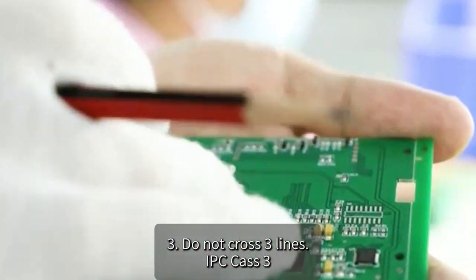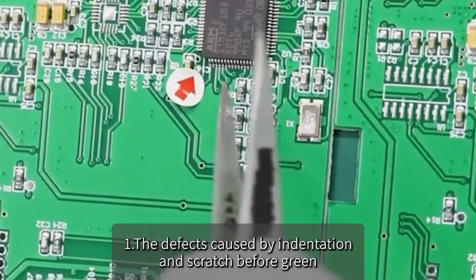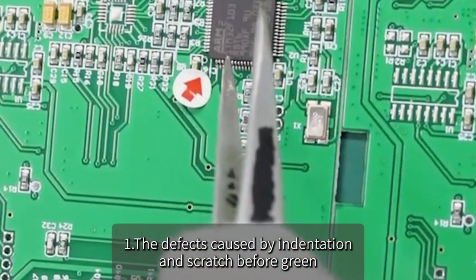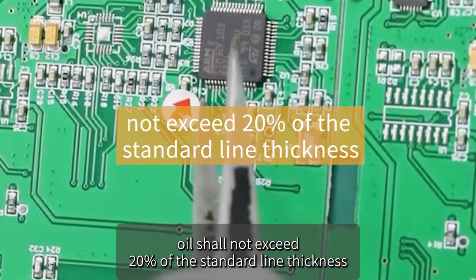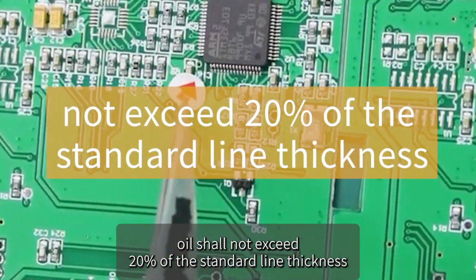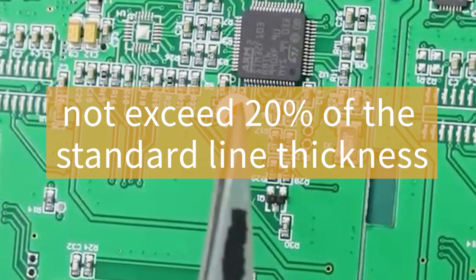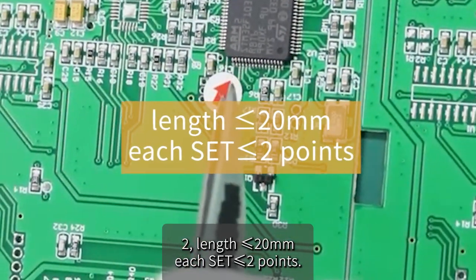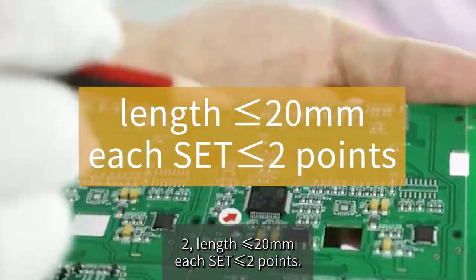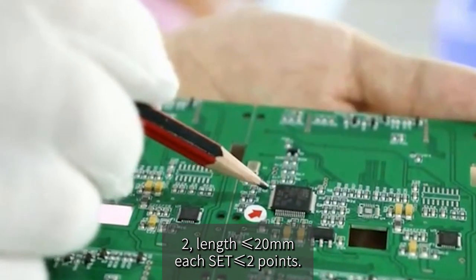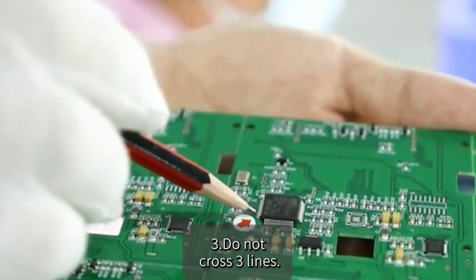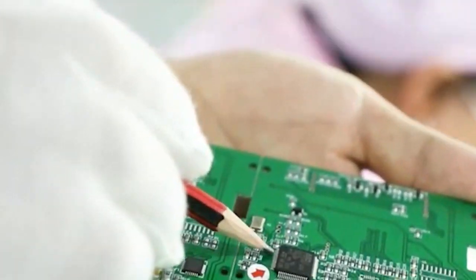IPC Class 3. 1. The defects caused by indentation and scratch before green oil shall not exceed 20% of the standard line thickness. 2. Length less than or equal to 20 mm, each set less than or equal to 2 points. 3. Do not cross 3 lines.